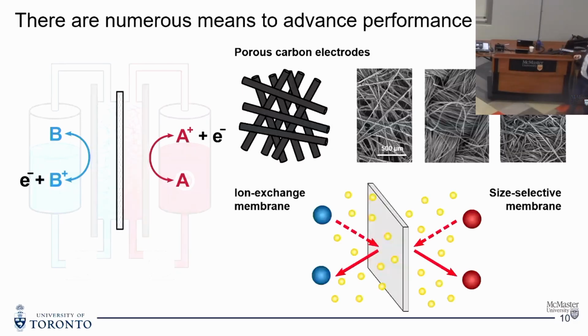And then lastly, the cell is separated by some sort of ion exchange membrane. So something that allows our supporting salt ion, these little yellow dots, to pass freely through the membrane, but keeps each of our species on its respective side. If those go from one side to the other, they are essentially lost, and we lose the energy storage capacity of those species. So we want something that is selective and keeps those on their respective sides of the cell.